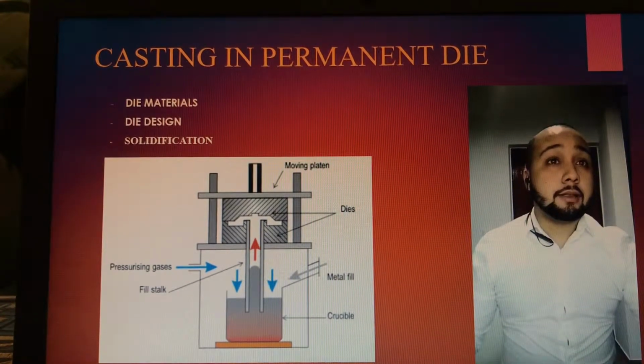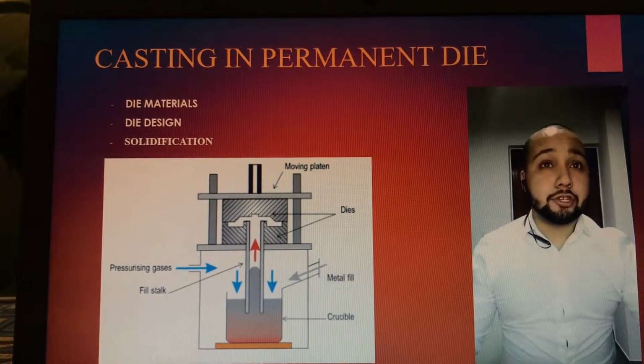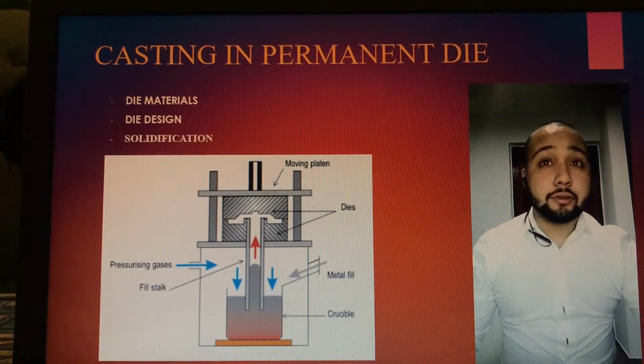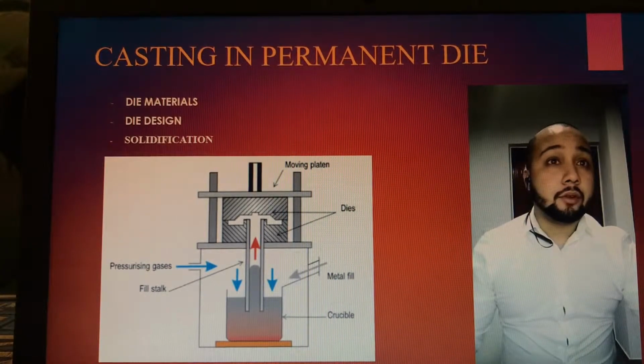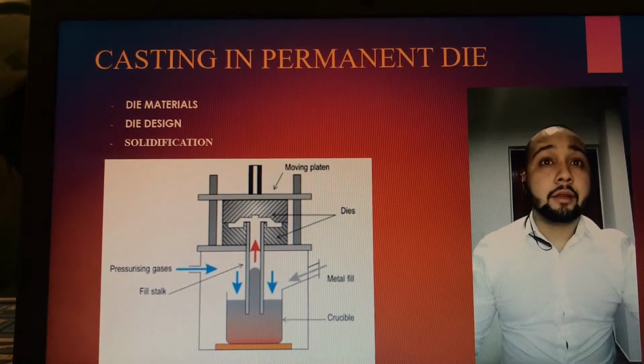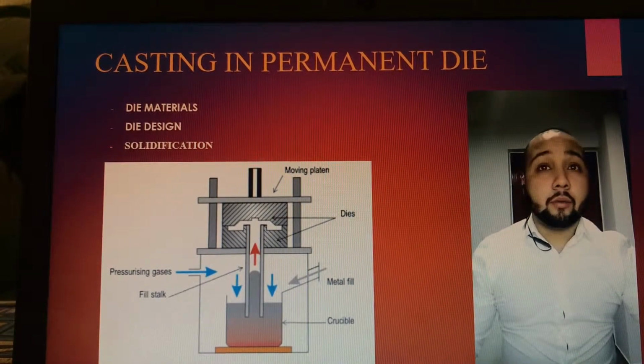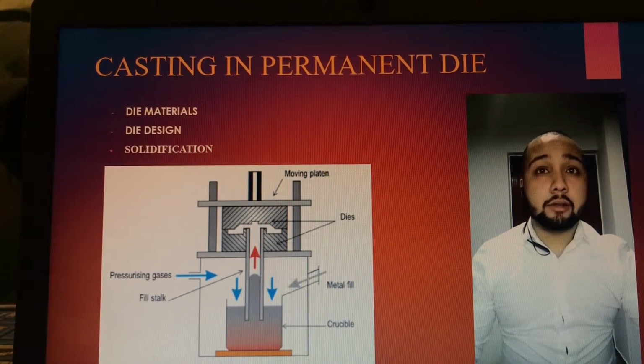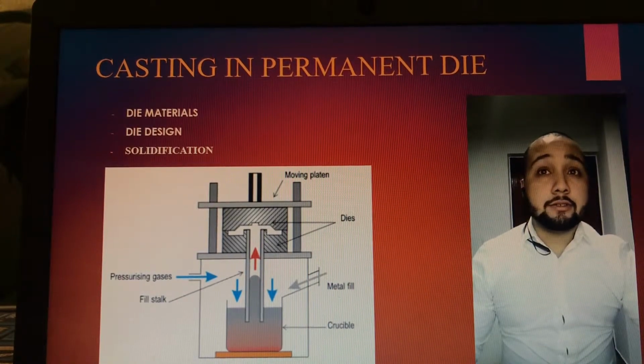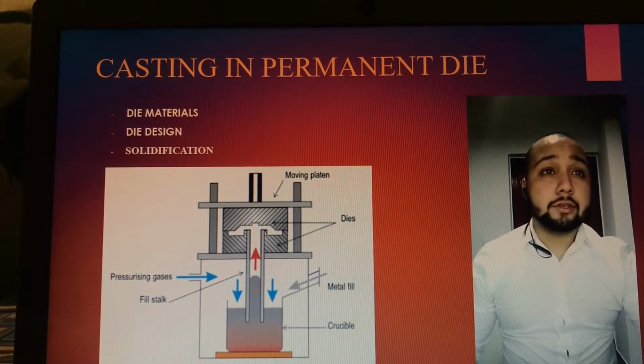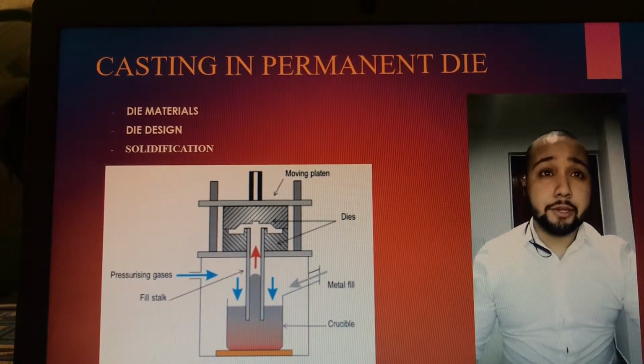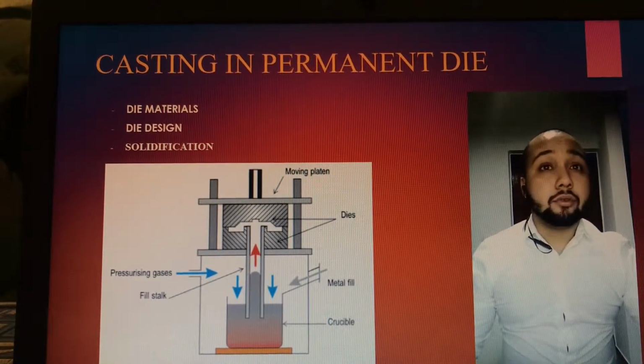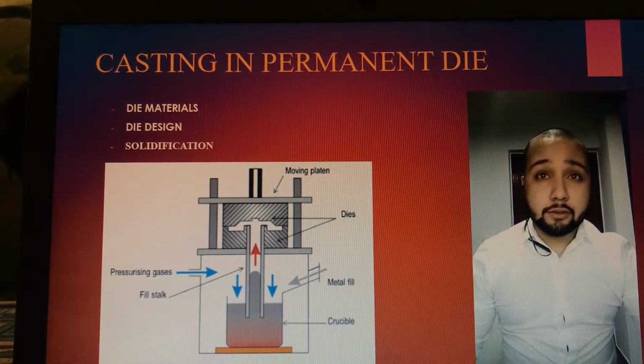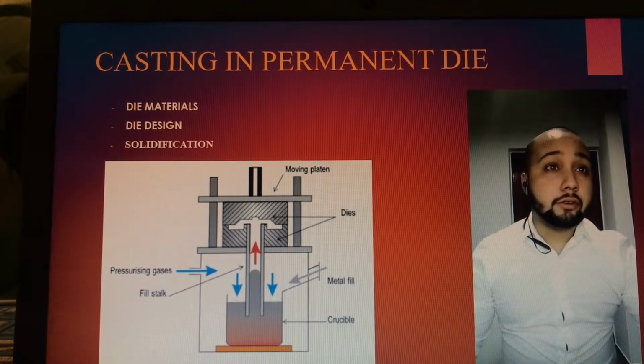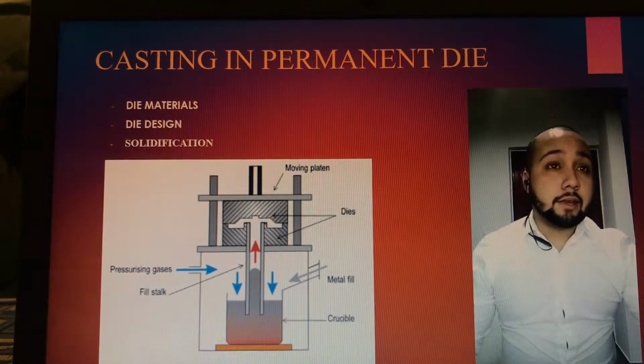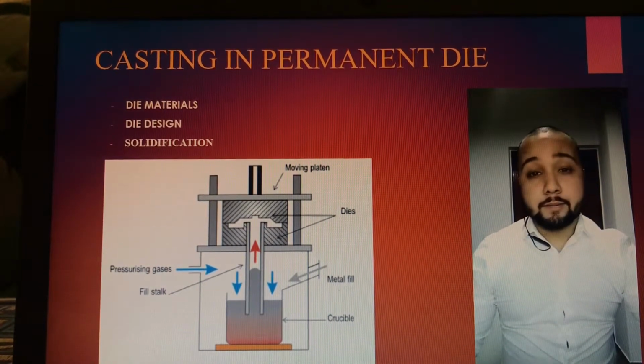Solidification. The permanent mold works like a heat exchanger. At the start of production, the mold must be preheated to the desired temperature, generally between 150 and 200 Celsius degrees for zinc, 250 to 275 Celsius degrees for magnesium, between 225 and 300 Celsius degrees for aluminium, and 300 to 700 Celsius degrees for copper alloys.